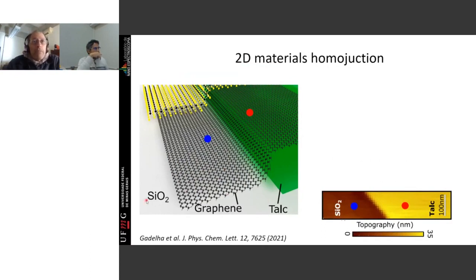Let's say that you have silicon oxide, which is the gray, okay, and then you put a material here that's represented in green. This material is talc. And then we know talc strongly dopes the material if you put it on top of the talc. Okay, so let's lay down a sheet of graphene, and half will be on the talc and the other half will be on the silicon oxide. And later you could look at MoS2 also, but let's stick with the graphene here. If I make an AFM here, if I control the topography, this is the image I get, okay? So this is the lower situation, this is the higher situation because you have the talc here. So I see the interface.